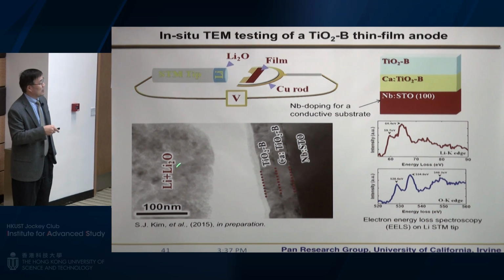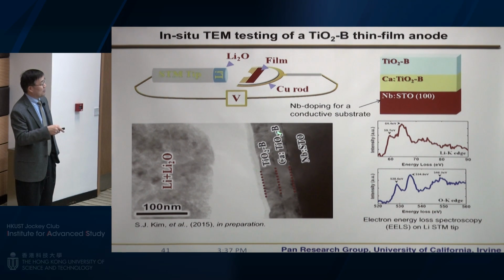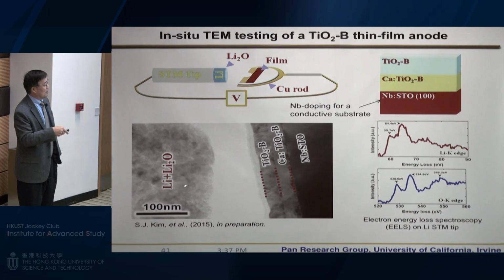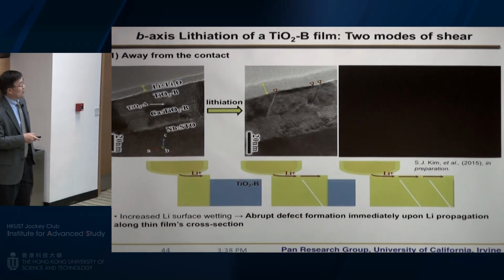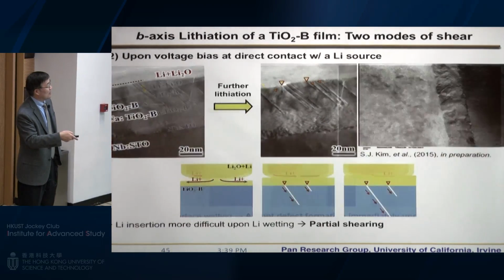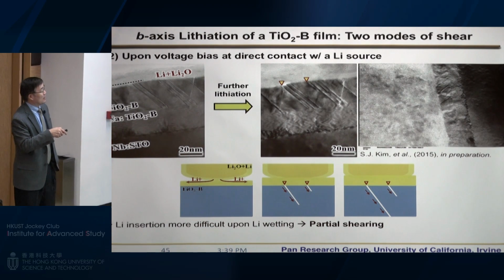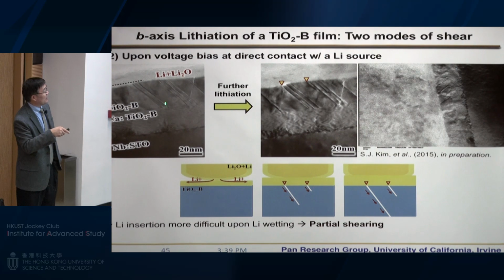This is Sangju's in-situ TEM work on this epitaxial titanium bronze B. We used niobium-doped STO as a bottom electrode, with a field across the lithium and the niobium-doped STO. And I want to show you some defects that are seen in this. It doesn't allow me; I think I just didn't get this file very well. So you can see that applying an electric field between lithium and the conducting STO introduces a lot of planar defects.